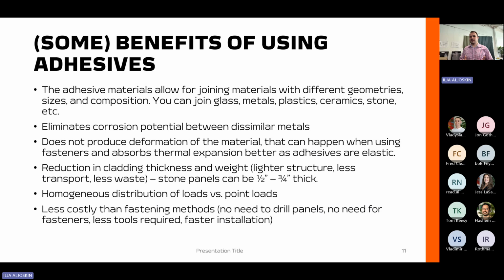and it also eliminates the corrosion potential between dissimilar materials. For example, if you're attaching a steel panel to an aluminum substrate, typically you would have a potential for corrosion because of the two dissimilar materials. And now you have an adhesive separating them. This is why it's also used in the automotive industry, airplane industry, because it allows you to bond these different materials without the possibility of this galvanic corrosion.